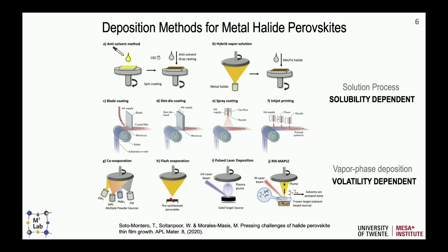But there is a challenge because there is a lot of solution process, but when you think about solution process and you think about the halide perovskites, the compositions are very complex. So you need to use these salts, these precursors, and you need to find the right solvent to actually deposit that material. So you have kind of the limitation of solubility, what I call solubility dependent. And that's why you need to go for solvents like DMF that are toxic, and then you need to combine 3 solvents and so on. So it also doesn't become so sustainable, but of course, we have to think about also the application. But that's basically the challenge of solution process.